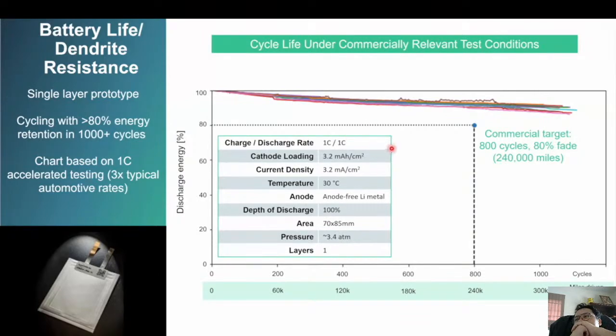So we're also trying to be transparent about the test conditions for every test. And so we'll give you the test conditions here. This is at a 1C rate, so 1 hour charge, 1 hour discharge. That's pretty aggressive for a cycle life test like this that's typically done at C/3, meaning 3-hour charge. So this is 3 times higher current density on every charge. The cathode loading of north of 3 milliamp hours per square centimeter is getting thick enough to have real energy in the cell. The temperature of 30 degrees is near room temperature.